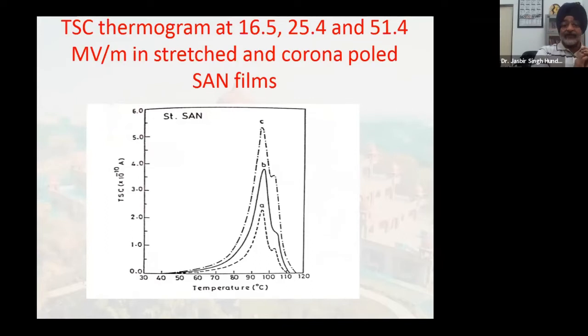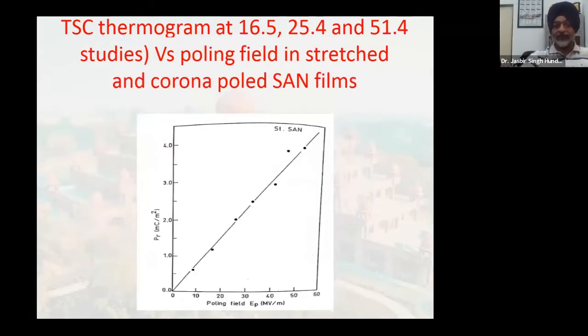Now, why these studies? Because we can find out the polarization in the film under different conditions by TSC. By measurement of the piezoelectric coefficient D31, the active polarization can be measured. So polarization can be measured in two ways. One is by calculating the area under the thermally stimulated current curves, or by hysteresis studies, right? The values should come out to be equal, and the linear dependence on poling field and other things can only be studied here. So this is what we actually found.